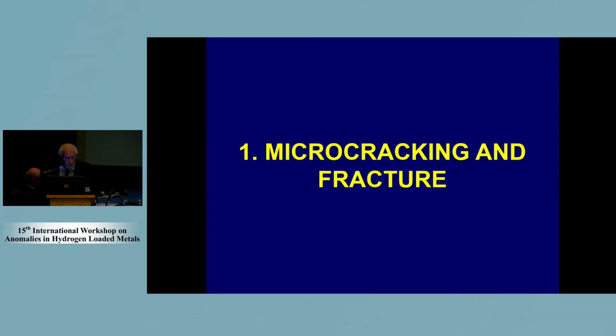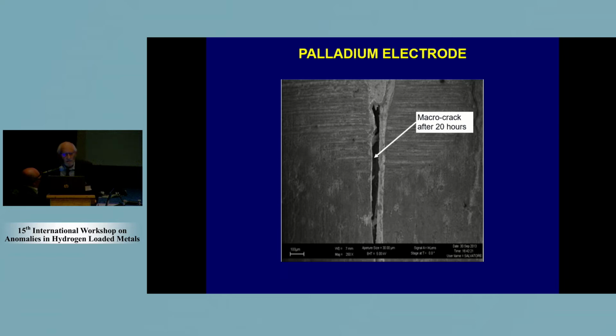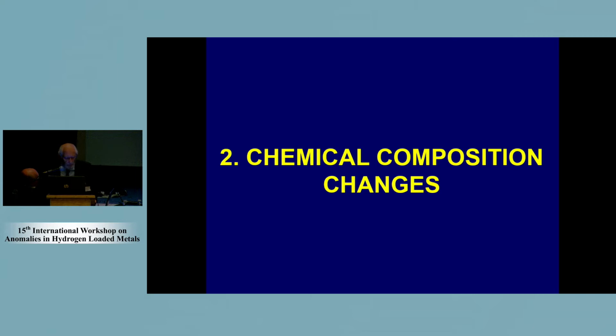So section 1 is related to fracture. I will be very short, even if we have a lot of observations, also a diffused damage in some cases, which evolves during the time. And lastly, we have, in some cases, even macro cracks. For example, in the palladium, after 20 hours of our preliminary tests, we had this crack, which was about 2 millimeters long, and the width, so the distance between the two crack faces, is about 40 microns. This is a micrograph, of course. So I show you only that, but we have different interesting micrographs.